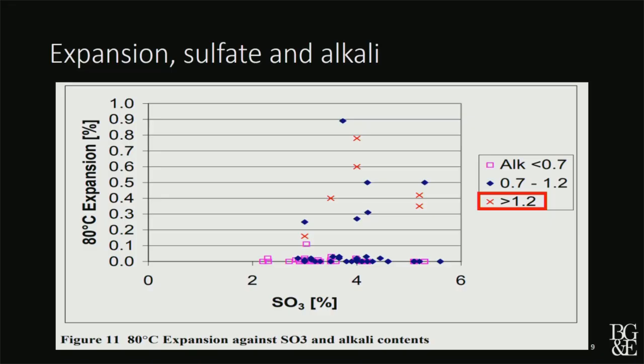So this is another graph that he produced, and it shows that depending on the alkali content and the sulfate content, the cements may show different expansions. And so this data is very similar to what we just saw on a wide range of cements. And this work was produced a good 20, 25 years ago.